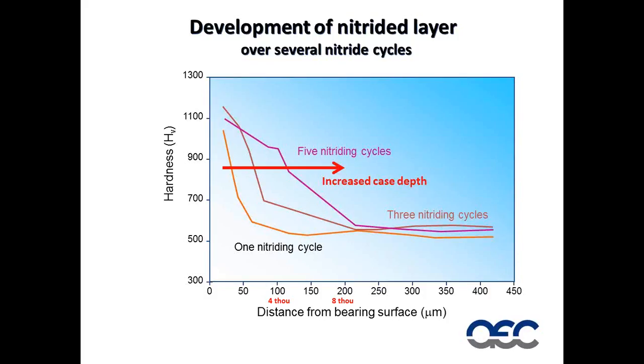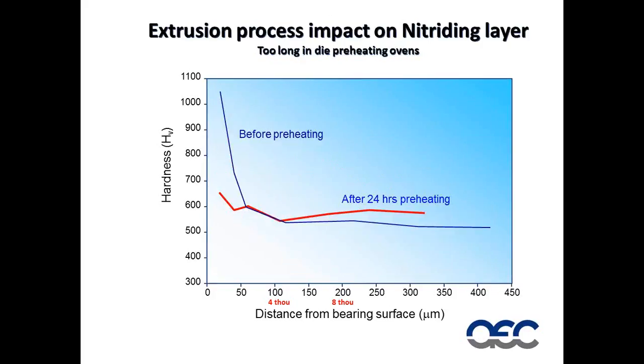Let's look a little at what happens when we put a new die with just one nitriding cycle into our die ovens. The blue line shows you the hardness profile of this die prior to going in the die oven. If we leave the die in the die oven for 24 hours, the red line is now the hardness profile of the surface of the die.